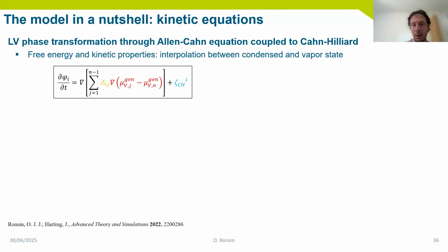Now I would like to emphasize some points in the thermodynamic properties. So let's have a look at the free energy. It becomes a little bit more complicated. Here, let's forget about what's shaded. You already saw that, actually. The only thing I want to highlight here is that we now need a description of the vapor, with the free energy in the vapor, which is basically the free energy of an ideal gas mixture. And then to handle the vapor and the liquid, the condensed phase, together, we just interpolate between the properties of the condensed phase and the properties of the vapor.